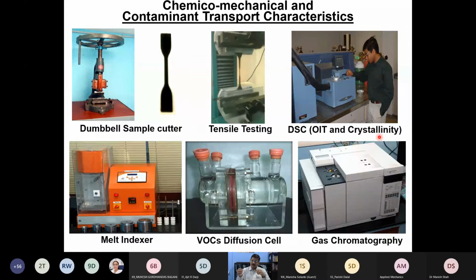The amount of antioxidant present in the polymer is measured by oxidative induction time using the DSC, differential scanning calorimeter. We have this facility in our lab, so you can really do that. Further, because of exposure to sunlight for a prolonged period of time, the polymer becomes subject to change. That means the molecular weight of the polymer is also going to go down.